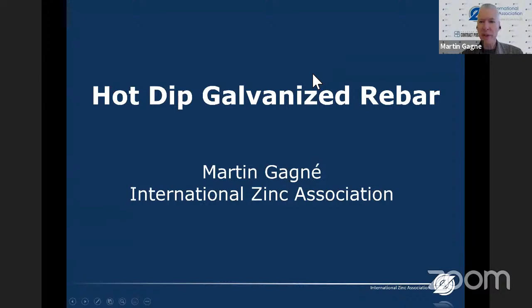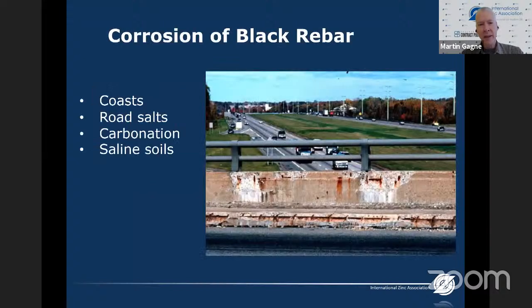Well, thank you very much, and I'm very happy to be here to talk about hot dip galvanized rebar. So people are asking, why should we hot dip galvanize rebar? So this is a bridge structure from North America. We can see quite extensive corrosion. Concrete is porous, and so as Simon mentioned, carbon dioxide can go in. Iron is quite passive at very high pH, but when the carbonation front arrives, it lowers the pH, which makes the iron susceptible to corrosion. And then chlorides, they can depassivate the iron and also start corrosion of the steel rebar.